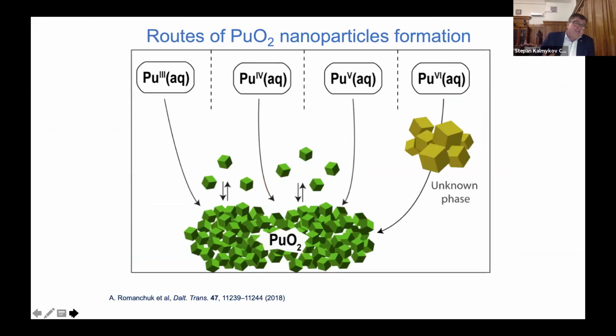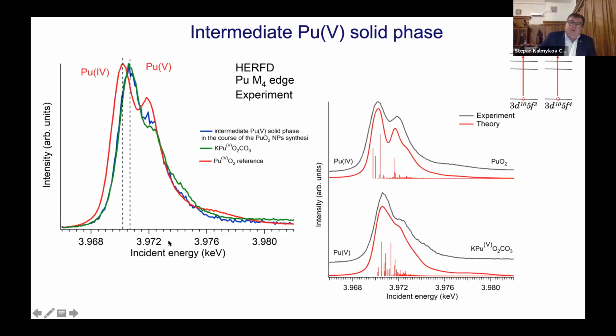The kinetics of this process is quite fast. Independent of whether we start with plutonium-3, 4, or 5, we have relatively fast formation of these precipitates that are aggregates of the plutonium nanoparticles. This is in contrast to taking plutonium-6 as the initial oxidation state. A very interesting thing is that the kinetics in this case are much slower. I will show you in the next slides. And the examination of plutonium-6, when we take plutonium-6 as a starting solution, gives us the clue that we have some intermediate plutonium-5 solid state.